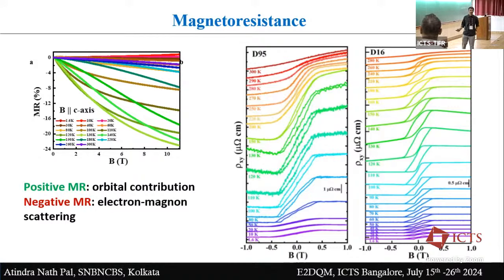You are right, but the transport data where these humps appear, we are not considering that much. The details we are not focusing on. But the main result is the resistivity data, where you see actually very nice contact. Now when we are making thin flakes, we are observing a contact resistance of a mega ohm or so, because thin flakes are very prone to oxidize. But in the bulk limit, the oxidation rate seems to be lower.